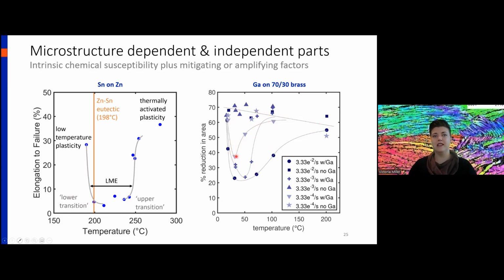So at these low strain rates, embrittlement is less severe because there's more time for thermally activated plasticity to be active. Whereas at these higher strain rates, there's less time for thermally activated plasticity, so you get this much wider ductility trough across different temperatures. And you need to get to a much higher temperature before ductility is restored. So that's the first half. There's microstructure dependent and independent parts.